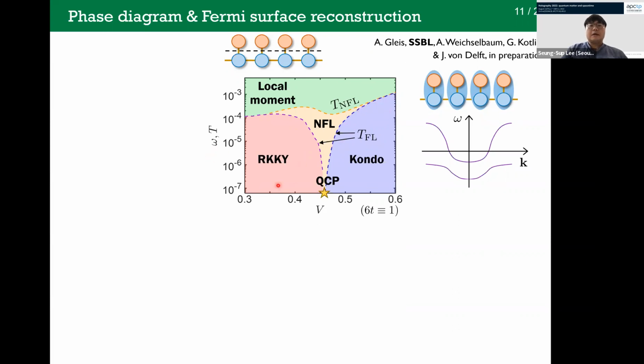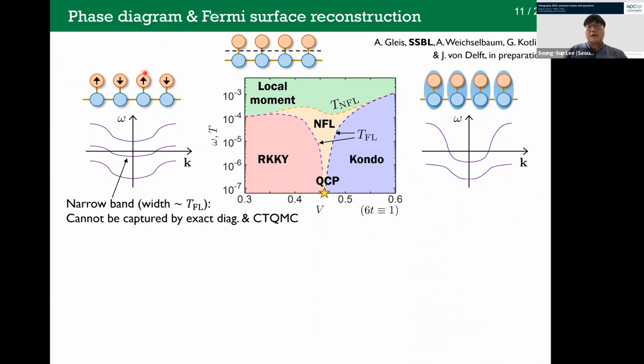And in the other case, the f electrons have a strong antiferromagnetic correlation. Interestingly, we found that there are three bands. As far as I know, nobody else could find this third band, which is very narrow, crossing the Fermi level. Its width is on the order of this Fermi-liquid scale, which is smaller than 10^-4 of the bare hopping amplitude. The existence of the narrow band could not be captured by the other methods. Only NRG can do this, because NRG is like a microscope that can resolve very small frequencies.